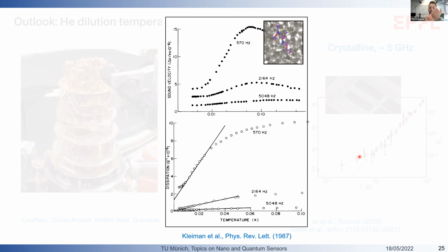So basically, defects, or two close-by minima in the energy landscape, given by displacement of a few atoms from the equilibrium position to another set of equilibrium positions in the thermodynamical energy landscape of the atomic lattice. So you have two minima which are just separated by a very small energy difference. The density of these two-level systems is predicted to be very high for glassy or amorphous materials, but should be much smaller for crystalline materials.